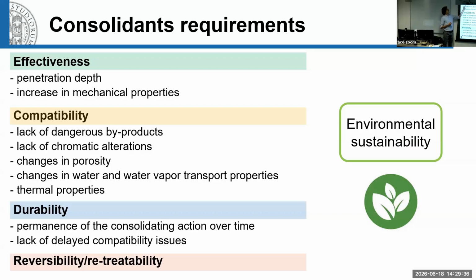So to be effective, it means that the new material should be able to penetrate in depth, because we don't want something that limits on the surface for a few microns. We need something that is able to provide action also in depth. It needs to improve the mechanical properties, okay, megapascal. But in doing this, it must be compatible. What do we mean? For instance, there shouldn't be any color change. If I have a white marble, I don't want it to become yellow or gray. But at the same time, also changes in the pore system, in the water transport properties, water vapor properties, and so on should be controlled.